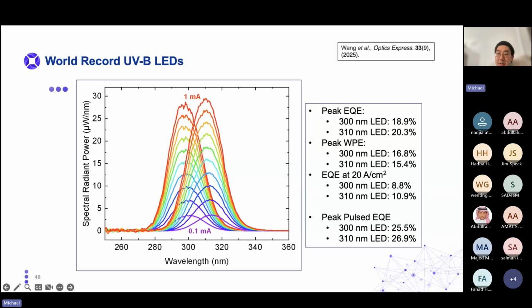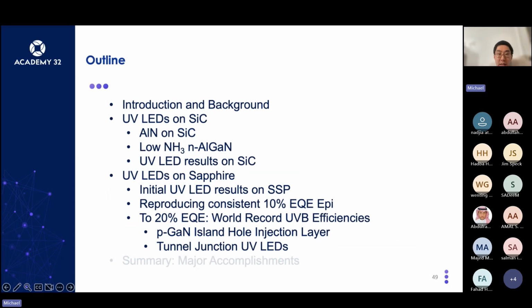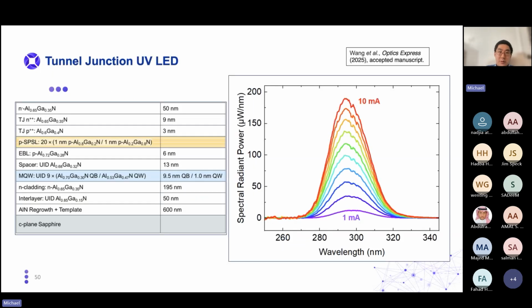Additionally, the peak pulsed EQE of the 300 nanometer LED is 25.5%, and the 310 nanometer LED peak pulsed EQE is 26.9%. Additionally, I also recently have an accepted manuscript on tunnel junction ultraviolet LEDs. So taking the work with this new optimized LED structure, I optimized a tunnel junction on top of this structure in MOCVD with just a one-pot growth with no regrowth and just everything under MOCVD.